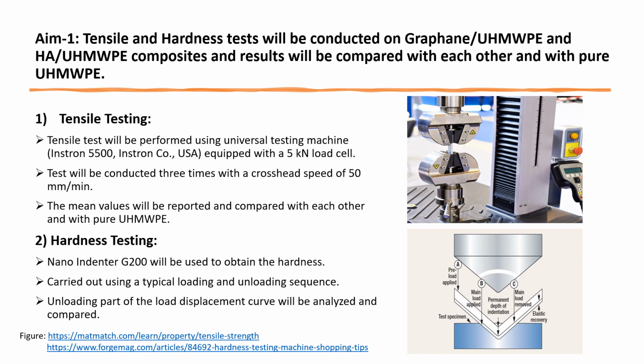The tensile test for the measurement of the yield strength, Young's modulus, and the elongation at break will be conducted using a universal testing machine with a 5 kN load cell. The test will be conducted 3 times and the mean values will be reported and compared with each other and with the pure ultra-high molecular weight polyethylene. For the hardness testing, a nano indenter will be used as shown in this figure. The typical loading and unloading sequence will be used and the unloading part of the load displacement curve will be analyzed and compared.